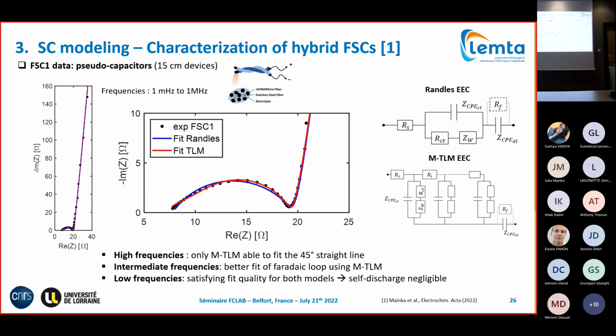Now, as well, a real physical reason means that you have a very high impact of your pore space on ion conduction. This is the same as the alpha exponent in your CPE, which will result in a depressed circle if you have impact of the pore space. The lower your alpha exponent, the higher the impact of your pore space on ion conduction, the more depressed is your semicircle, and the lower the slope as well. So both are possible.